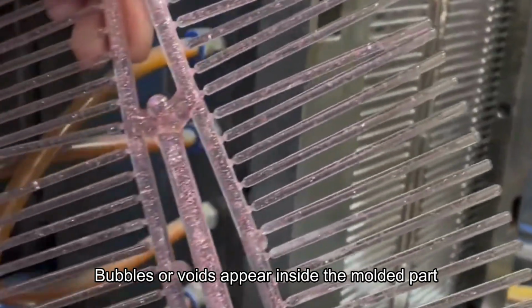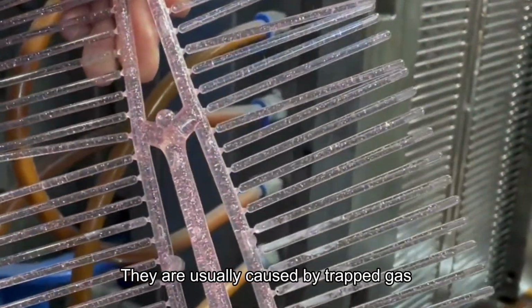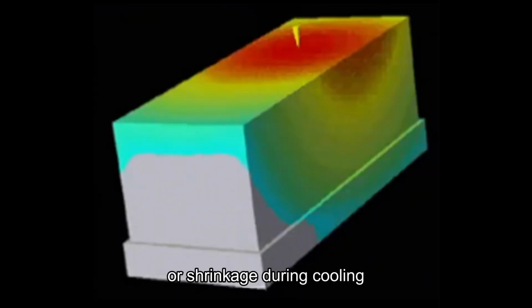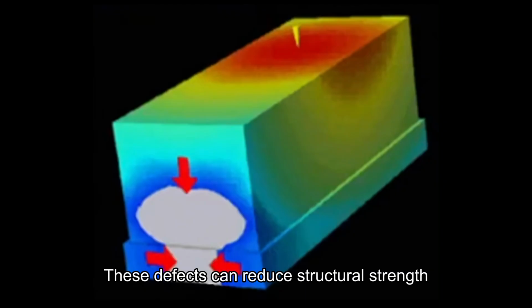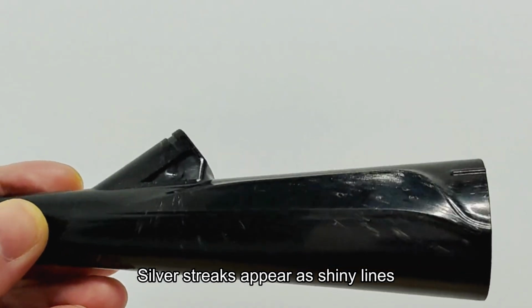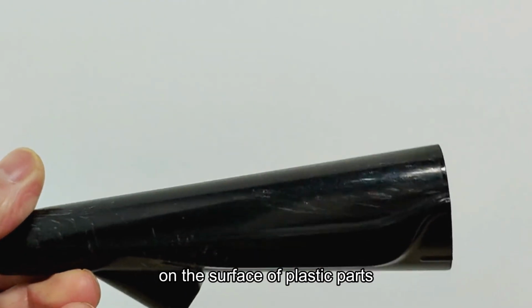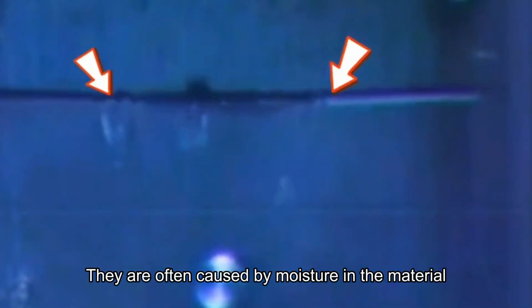Bubbles or voids appear inside the molded part. They are usually caused by trapped gas or shrinkage during cooling. These defects can reduce structural strength. Silver streaks appear as shiny lines on the surface of plastic parts. They are often caused by moisture in the material or insufficient drying.